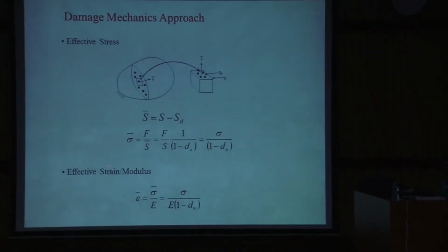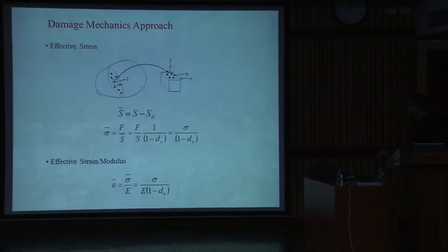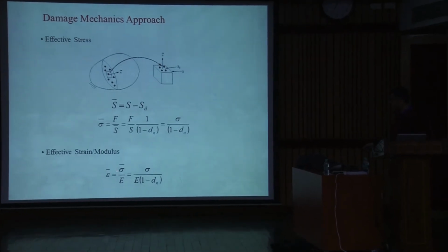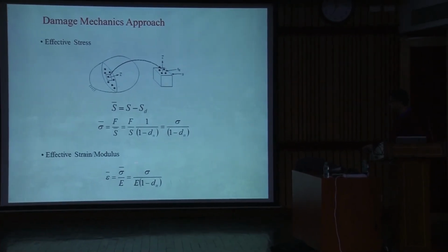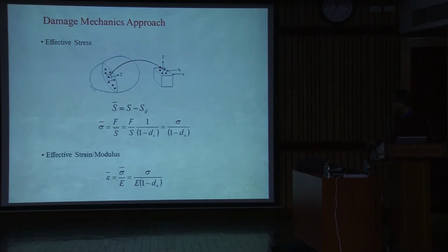If I further work with the stress-strain relation, I can also define the effective strain. If I replace the effective stress by this, then what I see is the nominal stress divided by this term, that is, E times 1 minus dn. E is your original stiffness. Because of the damage, it has now been reduced by this factor 1 minus dn. So the effect of damage can be characterized in the material through the reduction of the stiffness.